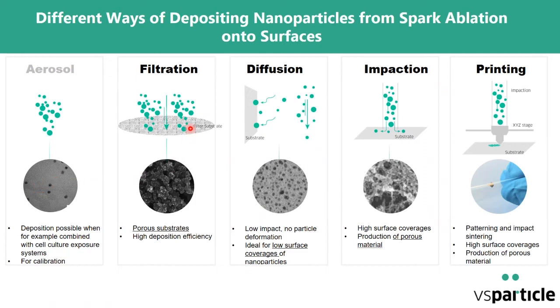One is filtration. You have a material that is usually a fibrous material, and lead the aerosol through a filter material, and then the first particles will stick in the filter material, and when you build up, then you can build up a cake on this filter material, forming a porous layer. If you want to gather only few particles, low surface coverages, and rather homogeneous coverages, you get that by using diffusion. So if the aerosol is flowing here and you put a substrate into this flow, then you rely on the diffusive motion of these particles, and some of them will hit the substrate, and due to van der Waals forces, they will stick there.